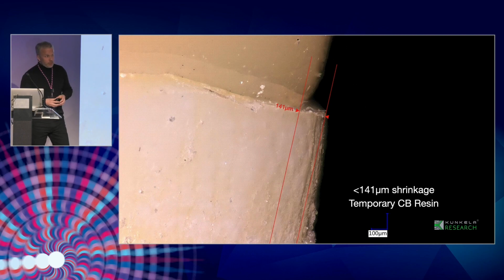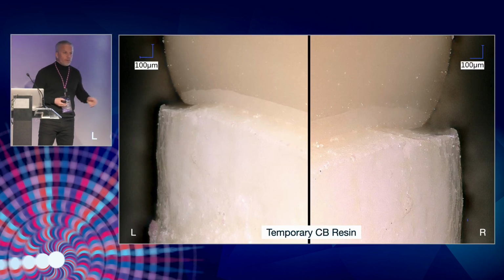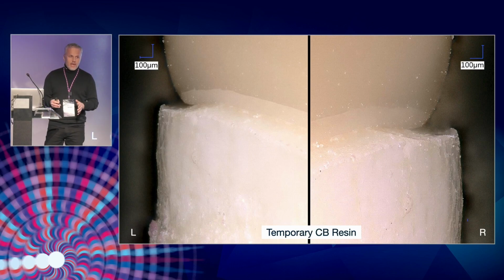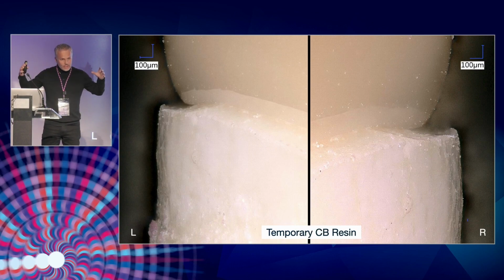printed material, especially if we are using not well improved curing machines, because for that one we used the curing machine recommended by Formlabs, and we sent the data to this company about this problem, that the curing unit does not fit well for the temporary resins because they are not highly filled, and that's why the shrinkage is bigger than the permanent material, but they don't care. I asked them if I can publish it with the audiences, with other colleagues. They told me, okay, so we are not responsible because it's not their material, but they are responsible because the curing unit is the problem.